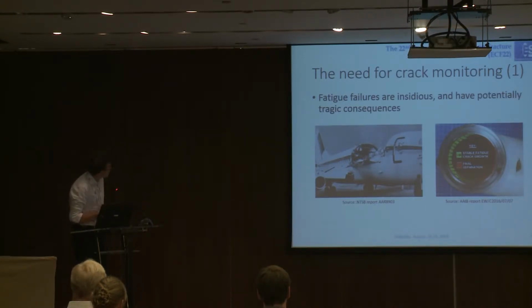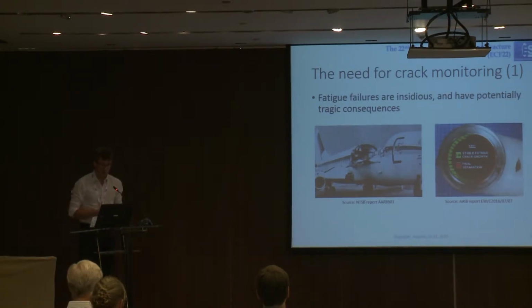The picture on the right is more anecdotal. It's the main landing gear of a general aviation aircraft that failed. And investigation has again proven that it was due to a fatigue crack. The reason I selected these two cases amongst a lot of them is that they have common characteristics that illustrate the need of performing in situ fatigue crack monitoring.